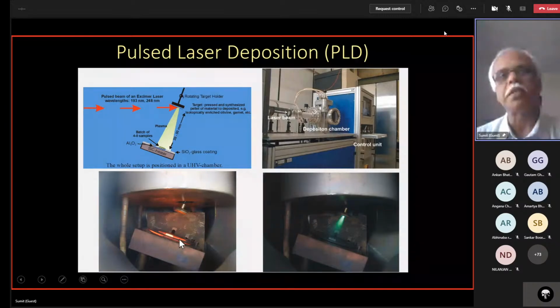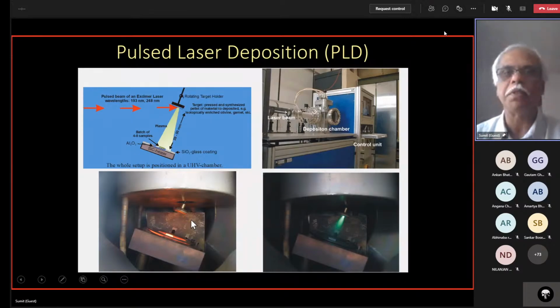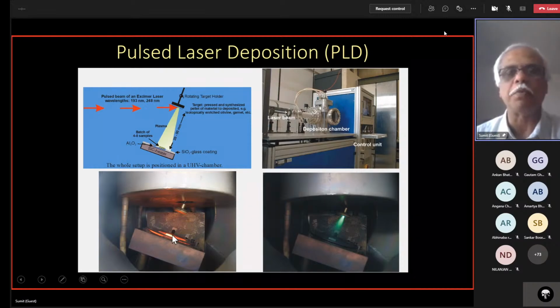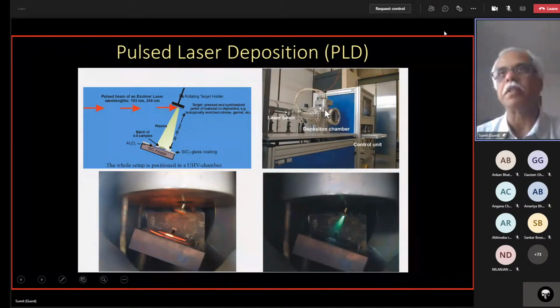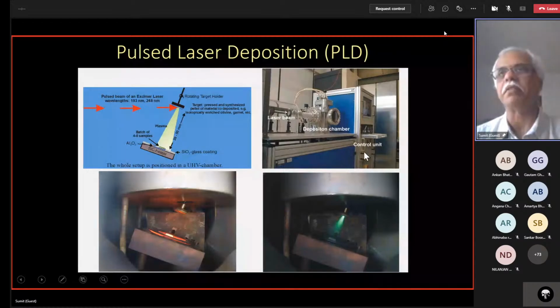And this is shown that we heat this chamber a little bit before we do all this deposition, because the surface of any material always has adsorbed oil and water and things. So you need to get rid of those. Just to put things in perspective, you see the whole picture here again on the right. The laser beam is coming from the left. You're looking at the inside of the deposition chamber here. On the right is a control unit with computers and so forth.